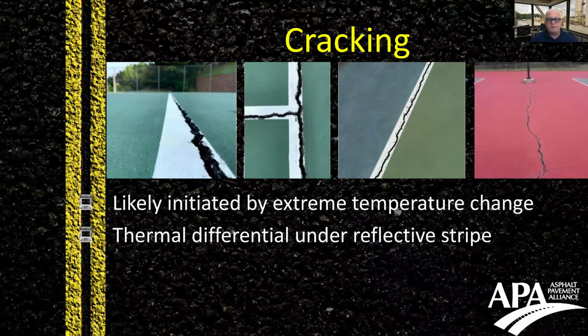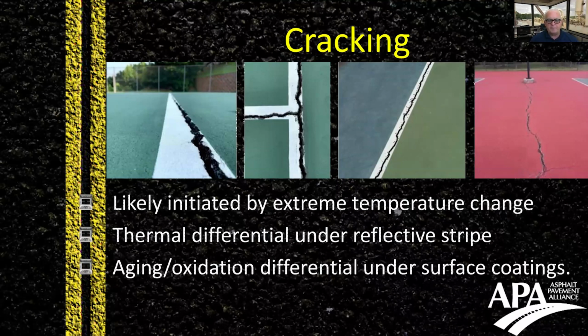You have big thermal differential under the reflective striping. In other words, the blue and the green and the red has a very different temperature than the striping that is applied to it. The white stripes reflect heat, and the darker colors absorb heat. So there's big thermal differentials under the reflective striping. And then you have aging and oxidation differentials under the surface coating.